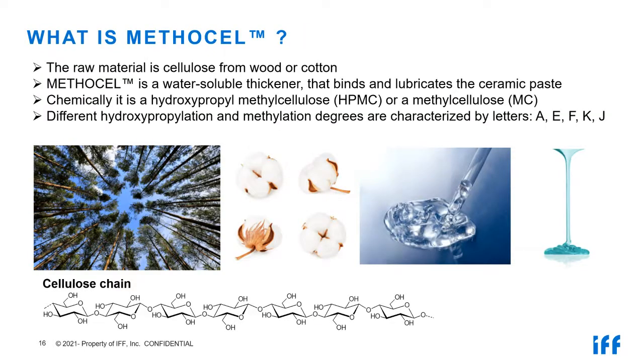At the end of the slide, you can see a segment of a cellulose chain, and you will easily see there are repeating units, so-called glucose units, and every repeating glucose unit has 3 free hydroxyl groups. And this is where the reactions take place, where the methylation and the hydroxypropylation takes place. And we can steer the degree of methylation and the degree of hydroxypropylation, and this characterizes the differences in properties of our cellulose ether. So for instance, the hydrophobicity and hydrophilicity can be steered and influenced by this choice of parameters. Next slide.